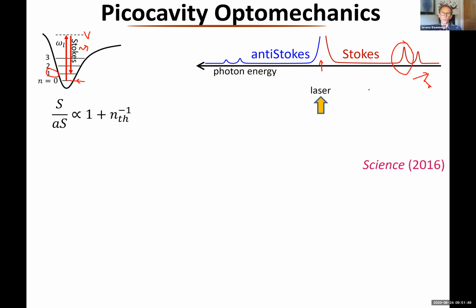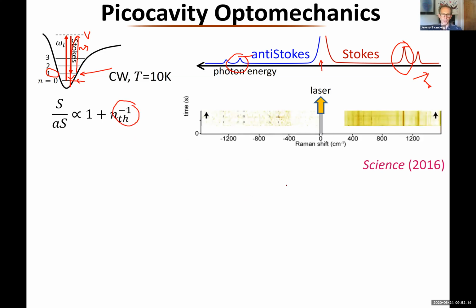I also have the possibility of going the other way around. I can first go up to here and then come down to the ground state. Then I'm going to get a higher energy photon coming out on this side here. And the ratio of this intensity to this intensity essentially tells me the population of this state here. So if I analyze this ratio, I find out the thermal population and I can measure the temperature. It's a nice way to measure temperatures.